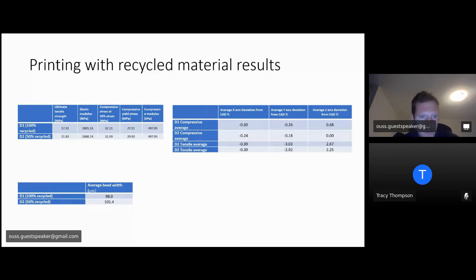Interesting, the average bead width for 50% recycled material is 101.4 and 100% recycled is 98. So there's a bit of a difference there. The recycled material is slightly bigger actually than what we'd expect from the 3D printed machine, which should produce beads at 100 micrometers.